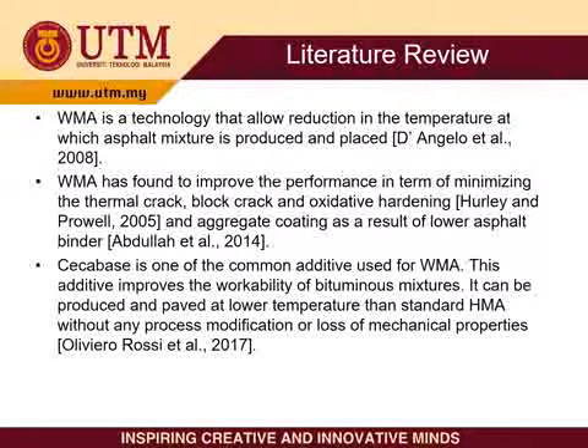Literature review. D'Angelo et al. 2008 stated that WMA is a technology that allows reduction in the temperature at which asphalt mixture is produced and placed. It is produced by adding either waxes, asphalt emulsion, or sometimes even water to the asphalt binder prior to mixing, and the temperature of WMA production normally ranges from 100 to 140 Celsius, which allows longer haul distance and cold weather paving, and a healthier environment in terms of reducing fuel consumption and emission.